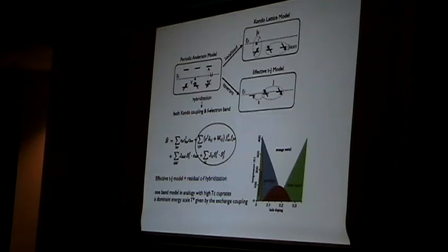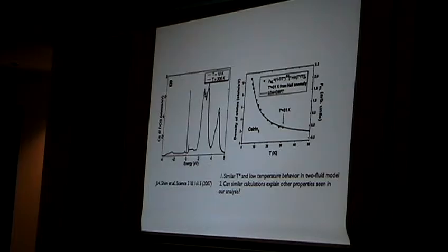All this leads to a question: what do we mean by Kondo liquid? We have these properties like susceptibility, Knight shift, and quantum oscillations. One possibility is if we think about the periodic Anderson model which describes the physics in the local region, we get a Kondo lattice model. In the weak hybridization region, we get effectively coupled to conducting electrons and every site has an RKKY interaction. So if this is weak, we get effectively a t-J model which is similar to high-Tc cuprates and has dominant energy scale given by the exchange coupling. This of course cannot explain all heavy electron physics and thermodynamics, but it suggests that maybe in heavy electron materials there is some way to include this hybridization to compete with dominant RKKY coupling.